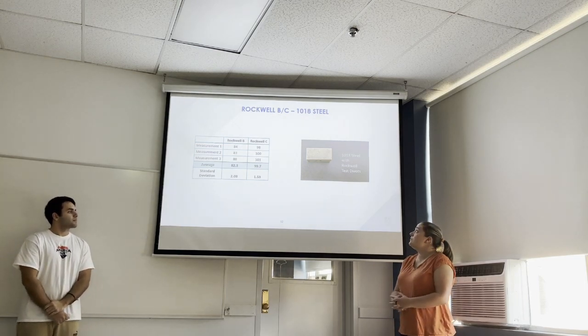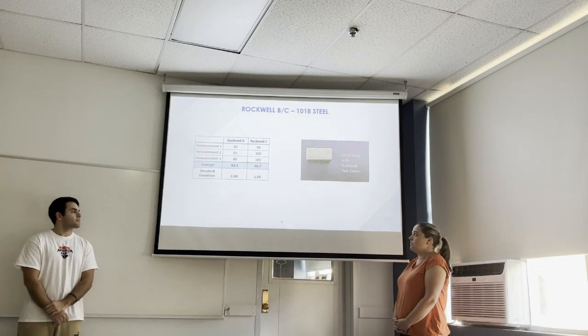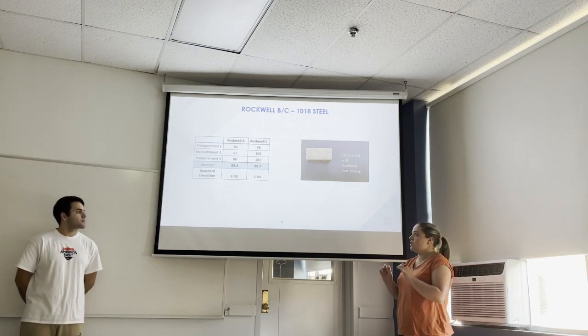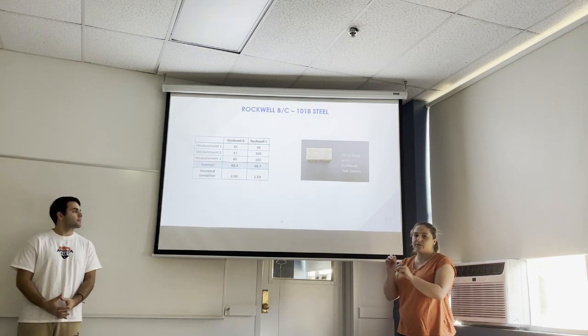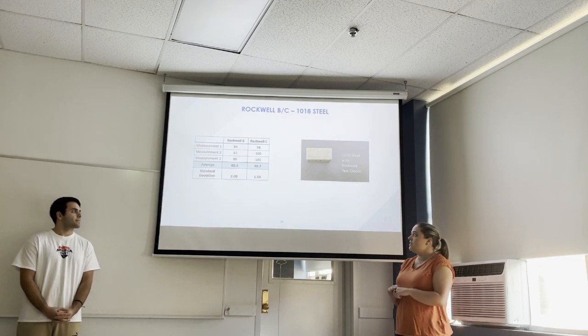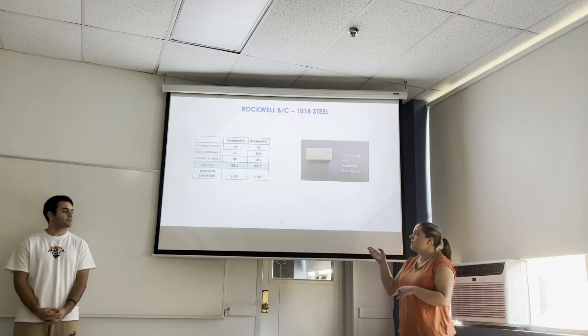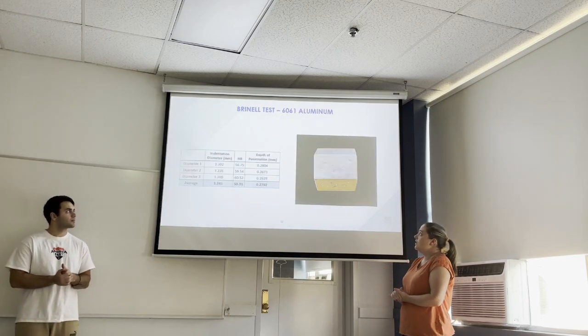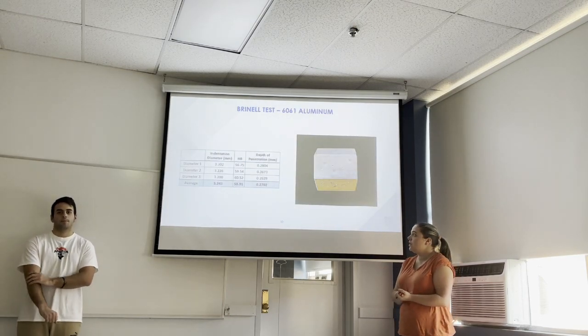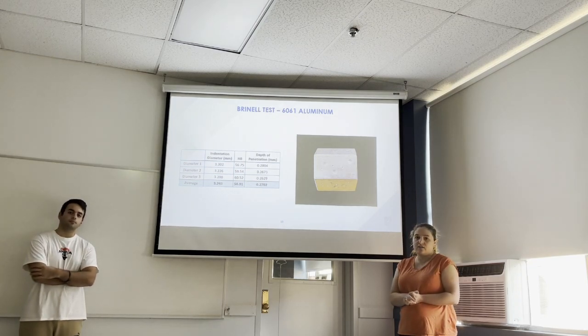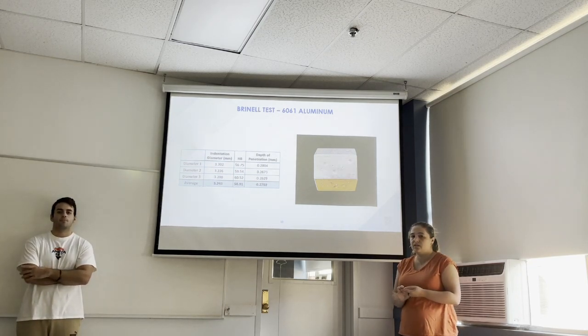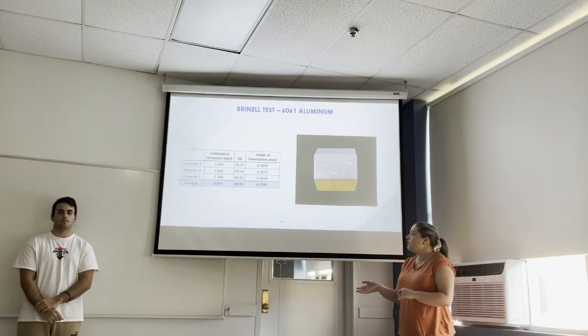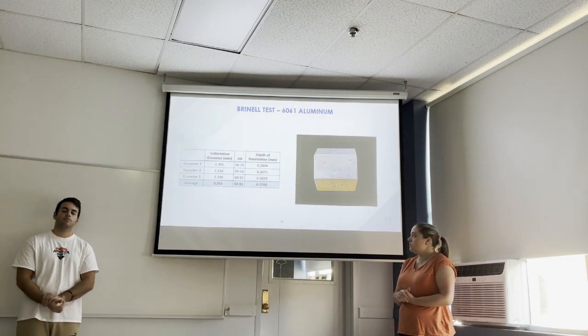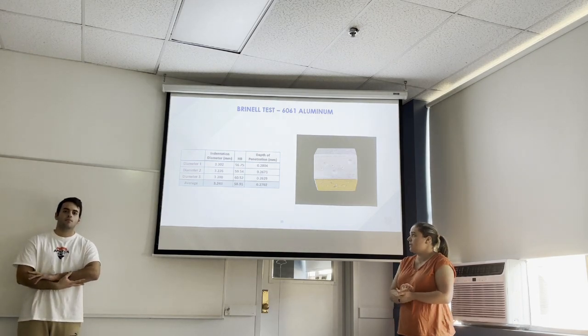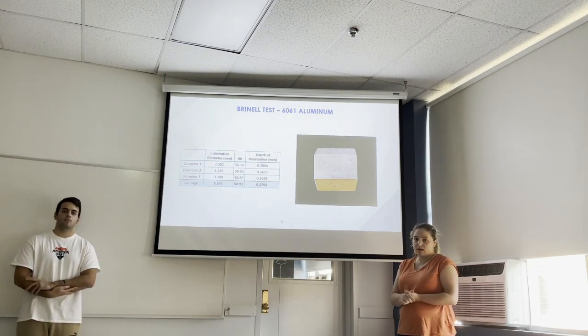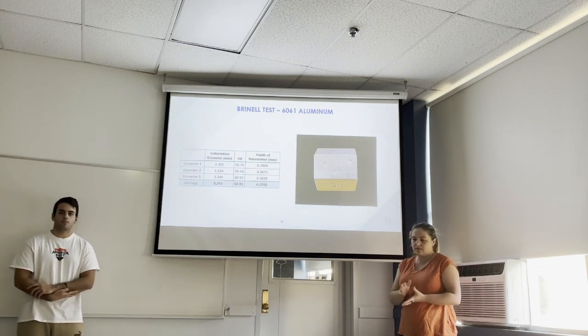For Rockwell B and C for 1018 steel, we use this to compare and see on average, is the Rockwell B number higher, is the Rockwell C number higher? And in this case, you can see that the Rockwell B average is lower than Rockwell C. For the Brinell test for 6061 aluminum, we looked at the indentation diameter and the hardness, which we calculated based on the equation that Riley presented earlier. And the depth of penetration was also calculated. We got an average depth of penetration of 0.27 millimeters, and then the hardness was about 59.